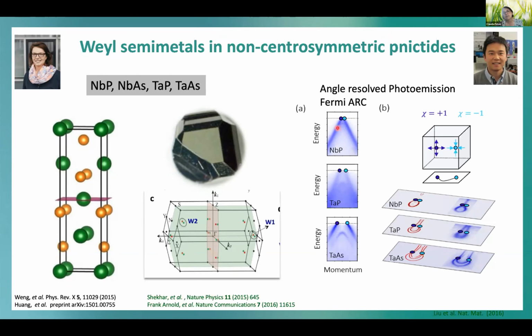But this was the first thing we did. We looked for the Weyl points in the material, for the splitting of the bands here which are related to the Weyl points, but the points are really artificial here - it's not a real measurement.